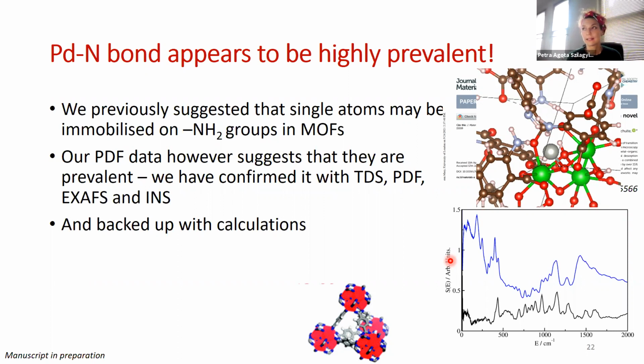And at the same time, the loading itself is not that high. In terms of weight percent, it would typically be below 5 weight percent. We have never been able to go above that. And because it's fairly randomly distributed, we haven't seen any issues with mass transfer that wouldn't occur in the empty MOF anyway.